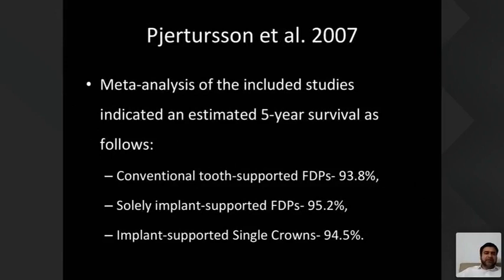Now, it was quite in tune with the study of Pjertursson in 2007, where he performed a meta-analysis of different studies, an estimated 5-year survival rate, where they proposed that the conventional tooth-supported fixed denture prostheses had 93.8% survival rate. Solely implant-supported FDPs had 95.2%, while implant-supported single crowns had 94.5%. And our study showed a 97% survival rate, which was quite acceptable.